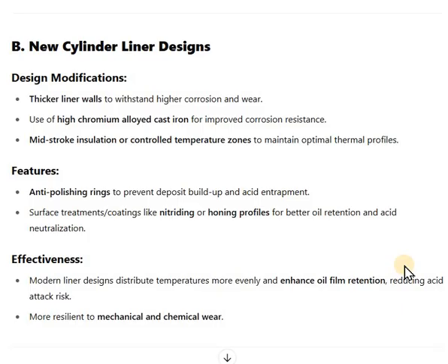So these points are quite important. The design modifications are the thicker liner walls, which can withstand corrosion and wear. The higher amount of chromium that has been alloyed in cast iron to improve the corrosion resistance. Mid-stroke insulation and controlled temperature zones to maintain optimal thermal profiles. And also the features that have been incorporated are the anti-polishing rings to prevent deposits built up and acid entrapment, surface treatment coating like nitriding and honing profiles for better oil retention and acid neutralization.